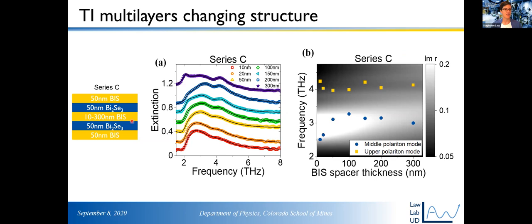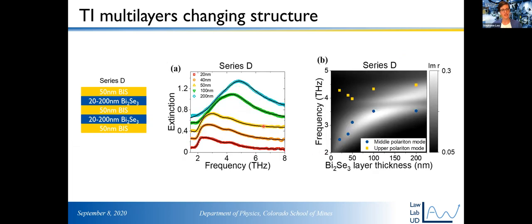So we can also do things like change the spacer layer and see how the modes move. And we can change the topological insulator thickness and see how these modes move. And again, the upshot of this is we actually do get some really interesting behavior for very thin layers where we get deviation from our model. And we think this is actually some quantum mechanical strong coupling that's not captured by our model.